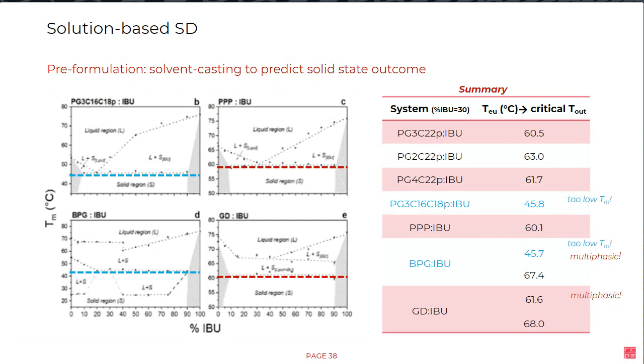We have here the phase diagram in combination with ibuprofen. I won't go through many details, but just to point out that everything which is in light blue, as you remember I mentioned, we chose this lipid on purpose to show how a low melting point may affect the process. The melting point of the original material is low, and now in combination with ibuprofen it is of course even lower, down to 45 degrees.